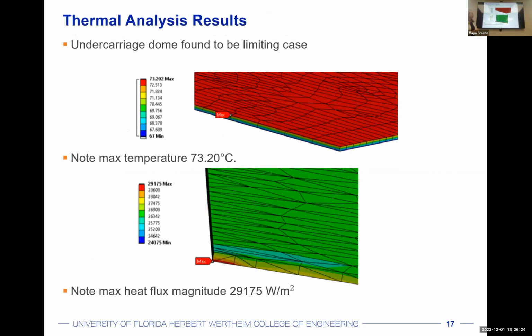The results, we found that the undercarriage dome was the limiting case. We did model both the undercarriage dome and the deflection skirt, and the undercarriage dome was found to be limiting. At the top, you see a temperature map. At the bottom, we see a heat flux map. In the temperature map, we see a pretty much constant temperature over the top of our image here. That will be the surface experiencing the regolith flow and experiencing the change in temperature. We found that max temperature to be 73.2 degrees Celsius, which is within the range of the titanium that we chose.